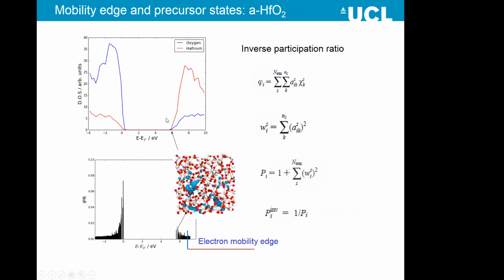So in order to find out where these electrons or holes can localize, we use what is called the inverse participation ratio method, which allows us to study the electronic structure of this material and correlate sites which are prone to localization by the behavior of the wave function to what might happen at the end.